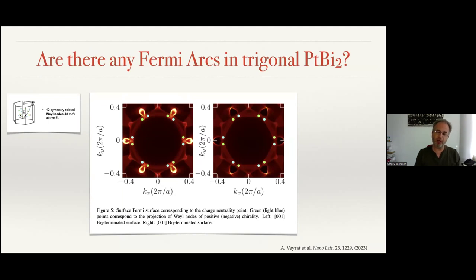In particular, at the surface of a Weyl semimetal, between the projections of the Weyl points I mentioned earlier, this is the place in the momentum space where the bands cross in a single point. So when these points are projected to the surface, between them there are states which are called Fermi arcs, and these surface states are rather unique because they are non-degenerate and they are different at different surfaces. This is termination A, termination B. They connect the Weyl points.